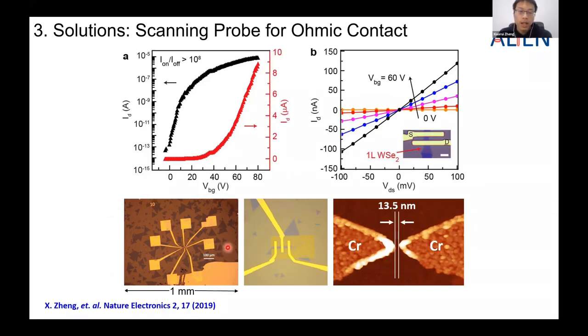Further on, we demonstrated the large-scale patterning capability of our lift-off process. You can see this is a whole bar structure. The scale size of these devices is like 1 millimeter. And another capability we demonstrated is the etching of the materials. For example, this one, we made an inverter. So the first step is to etch the triangle MoS2 monolayer into this rectangular short channel. And then by using the special overlay function, we can precisely align our electrode with the rectangular channel to form an inverter. Okay. In terms of resolution, so far the minimum resolution we could achieve is 13.5 nanometer.